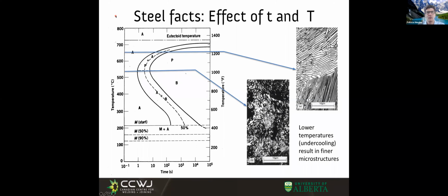When we quench into our salt bath - remember, our salt bath is kind of red hot here - I'm going to quench my steel into that salt bath, and at time 0, way to the left, nothing has transformed. We know that. At some time we have the start of transformation, a somewhat arbitrary definition, but most people would agree where it is, give or take. This line indicates, as we move in time, when the transformation starts. Then we keep transforming, and this other line corresponds to the end of transformation, which is somewhat arbitrary, but most people would agree more or less where it is.